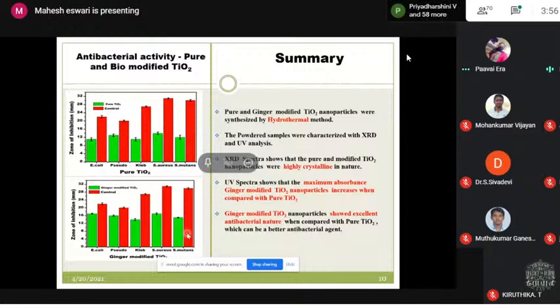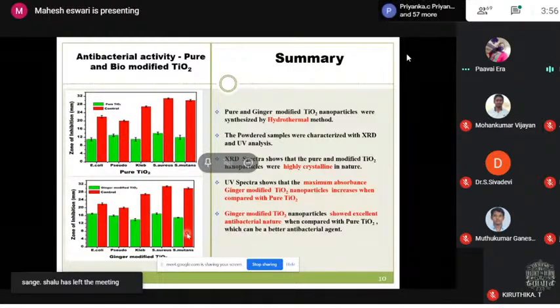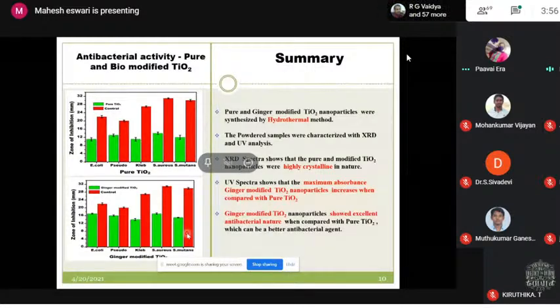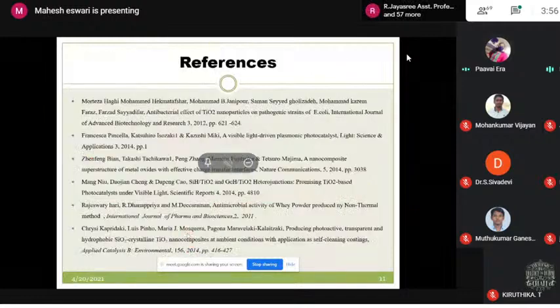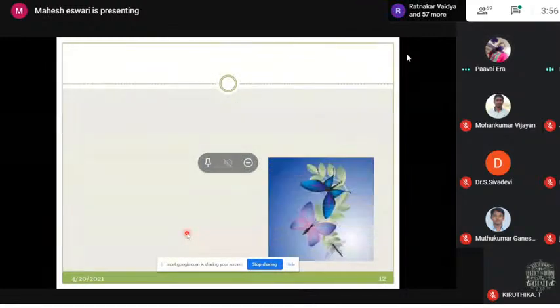This clearly shows, as a summary, that the pure and the ginger-modified titanium dioxide have been synthesized using the hydrothermal method, and the characterization has been done, which proves from XRD that it is highly crystalline. The maximum absorbance has increased in the UV spectra, and on the whole, my conclusion is that the modification with ginger has enhanced the antibacterial nature. These are the references. Thank you. And our paper is published in Elsevier journals. I also give my acknowledgement to Shizuoka University, Japan, for the TEM analysis.